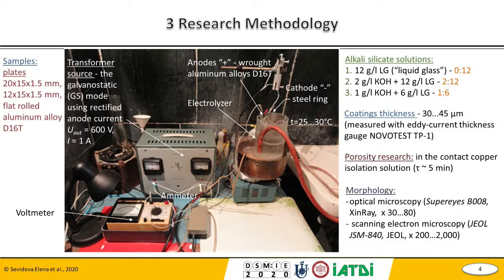The most interesting thing is that for volume resistivity measurement, we have used some contact electrodes and a copper collector, and for electric strength measurements, we have used other devices such as a high voltage transformer, protective resistors, and a device for smooth voltage. And after that, everything was calculated according to equipment. Next slide, please. And our results.